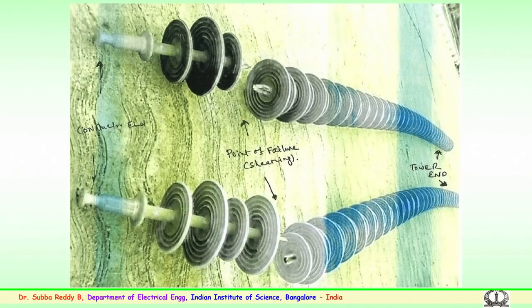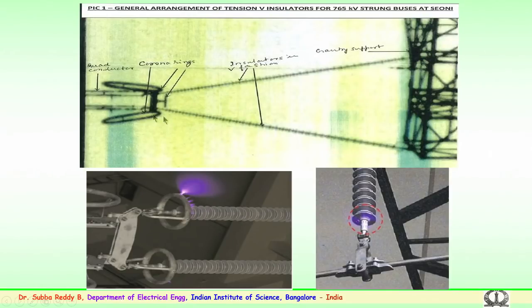This was evaluated, and the reason was the placement of the corona control ring. The placement and the design of the corona control ring, as I mentioned earlier, is very important. The corona discharges from the corona control rings continuously over a period of time are impinging on the surface. So, this corona control ring causes corona at any instant, and during foul weather conditions this could aggravate, and this entire insulation portion could damage the surface.